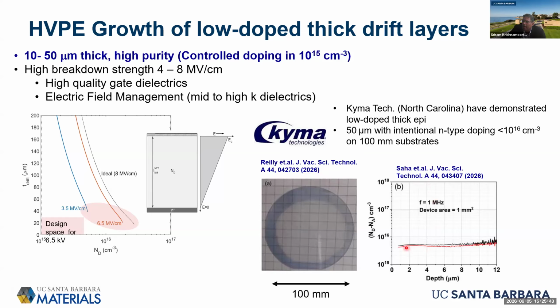So this is work done by Kyma, and we had access to some of this EPI through our project, and we've been able to do high voltage CV measurements to confirm that actually down to more than 10 to 12 microns into the layer, the doping is flat, and it's actually in the mid-15s regime. And that's exactly what you need. You need mid-15s doping and tens of microns of thickness to be able to hit 6.5 kV, 10 kV, and these higher voltage devices. So lots of exciting progress in the last few years in terms of the epitaxial growth capability, both in Japan and in the US.